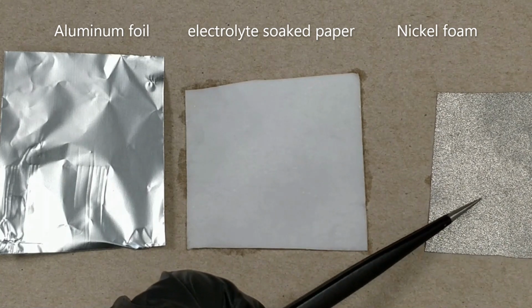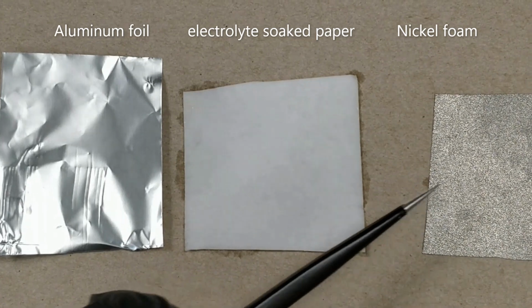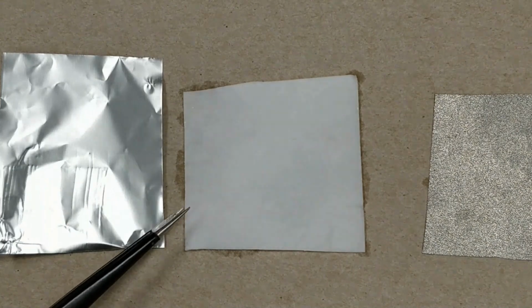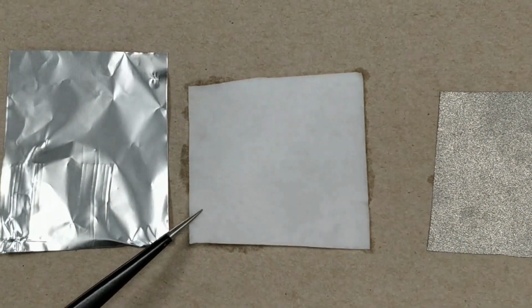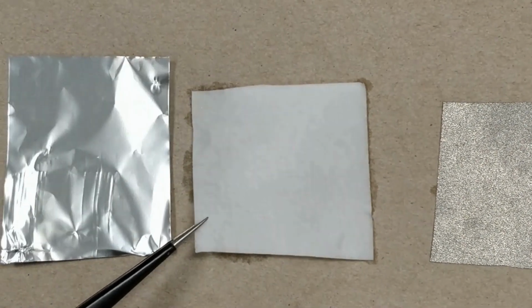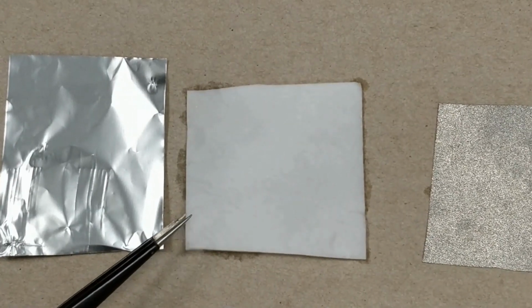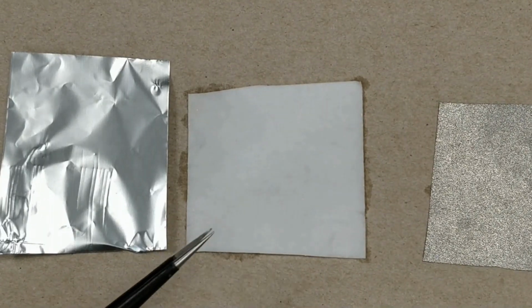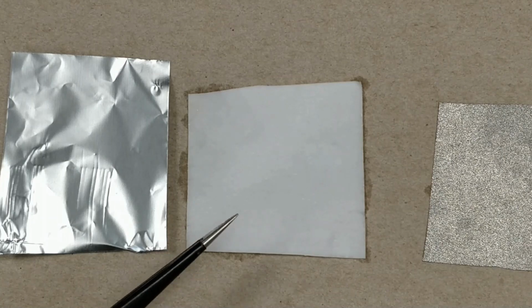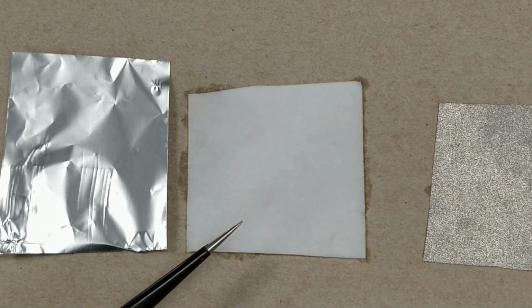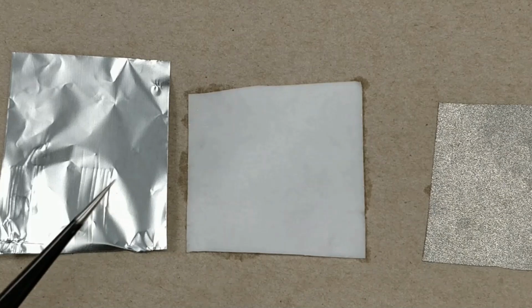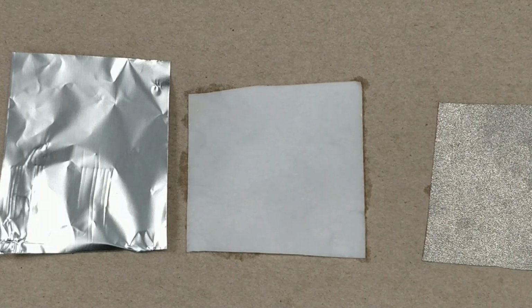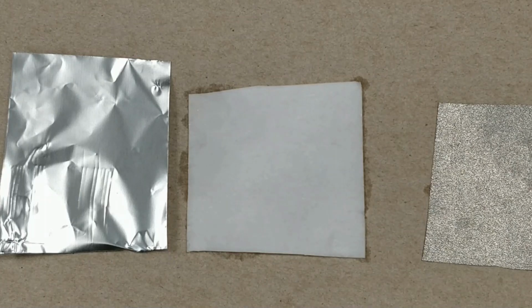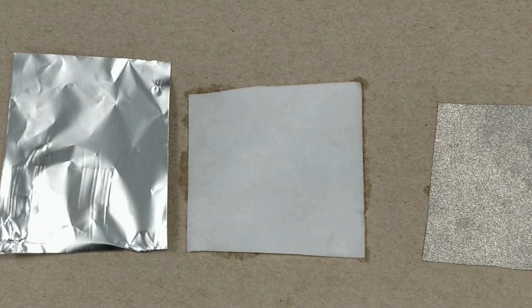In this system, nickel foam is not involved in the overall electrochemical reaction and only serves as a substrate on top of which oxygen gas from the air can accept electrons from the aluminum metal. Therefore, any other conductive and porous substrate can be used as well, such as charcoal paper. The overall electrochemical reaction is oxidation of aluminum metal at the anode to aluminum cations, reduction of oxygen to oxide anions, and formation of aluminum oxide in the electrolyte.